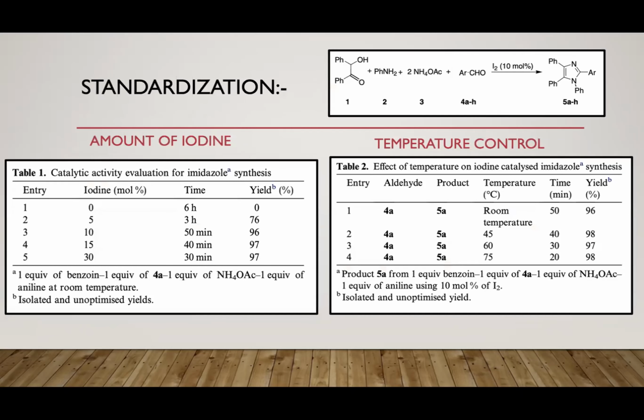Similar standardizations were done as we did for 1,2-diketone. Various mole percentages of iodine were tried, and in this case, the best result was with 10 mole percent of iodine. So we chose 10 mole percent as the concentration of iodine, and again various temperature levels were tried, and 75 we chose as the highest. We did not go beyond 75, because our intention was to go for a synthesis which is not very harmful, where we do not require any hazardous condition. There was improvement, no doubt, with the increase in temperature. But if you have enough time, you can prepare it at room temperature also. But our team prepared it at 75 degrees Celsius.